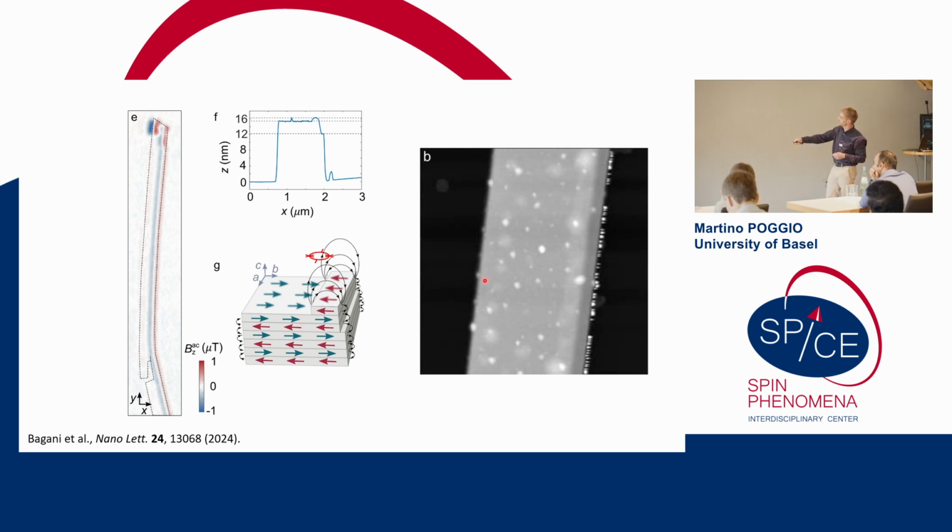And so what we had is this kind of a strip. So if you go over this strip, what you'll find is you have 18 layers, most parts of the strip here, and here where you see a little bit lighter, you have 19 layers, and then here you have 14 layers. And you can see the cross-section of that AFM here. Okay, so what you expect is to have just a little bit of signal from this very narrow strip here, equivalent to the magnetization of one layer, in the plane. And if you look at the image of the magnetic field out of the plane, that's exactly what you see. You see this kind of dipole-like strip, which corresponds to the stray field of this 19th layer. Okay, fair enough. So it behaves as you expect.